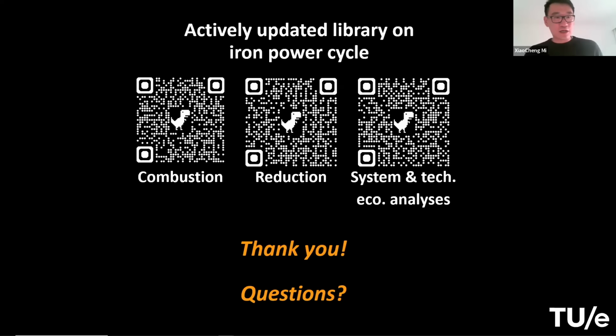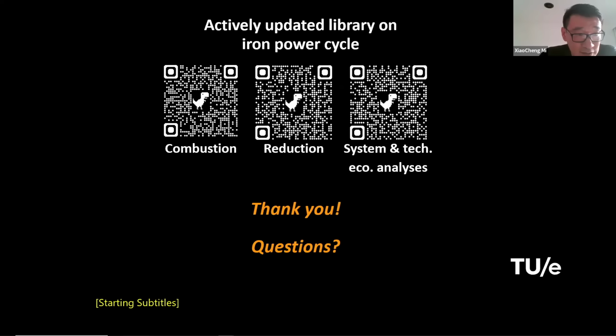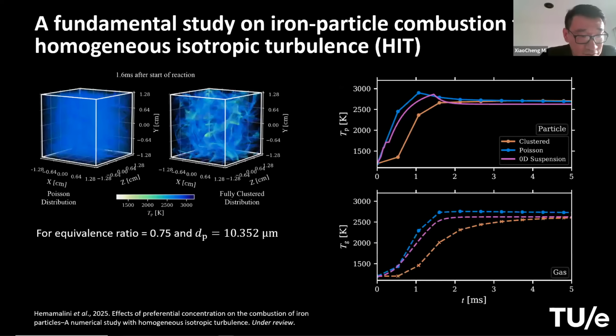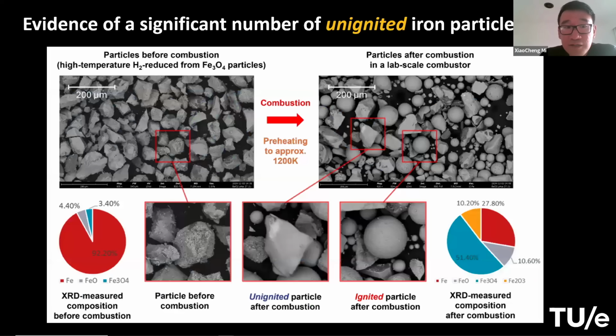Oh yeah, this we do. I probably didn't include anything here. Here I have one in my slides. Maybe not the most direct evidence, but we do have some more direct evidence. I'll just show you the one I showed in my slides. You see that this is actually one that failed to ignite, because on the left side, these are the particles after going through the combustor. You can see that before, because of the reduction, the surface is very porous.